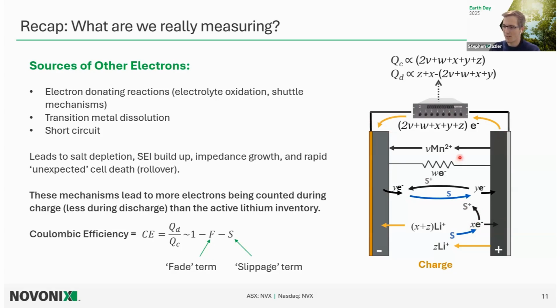Now, this sounds like a lot of extra electrons that we're counting, but all of these mechanisms in a good cell happen at very, very small rates. And a lot of the time, it's way below the detection limits of most equipment. The accuracy and precision is not enough to really capture this on a per cycle basis. So that's really the motivation, and how I'll build this out is talking about how to really encounter some of these mechanisms that, as you can see here, don't actually directly contribute to capacity fade at all. There's no lithium disappearing here. These are all excess electrons that we can count, but don't lead to capacity loss over time, but that will eventually lead to really bad things like our rollover failure.